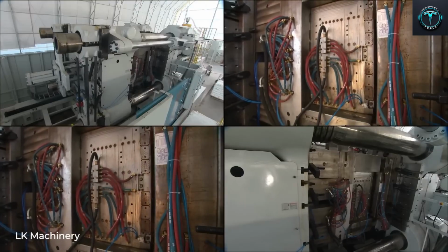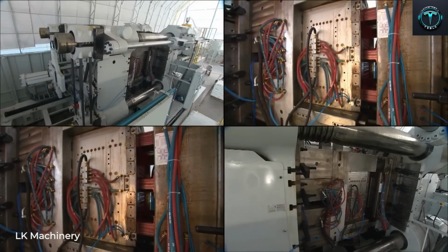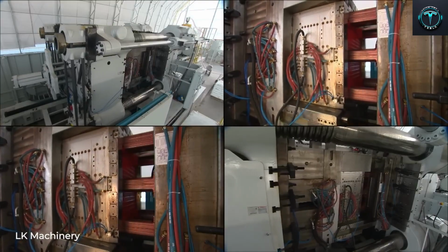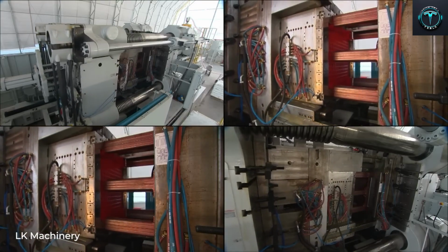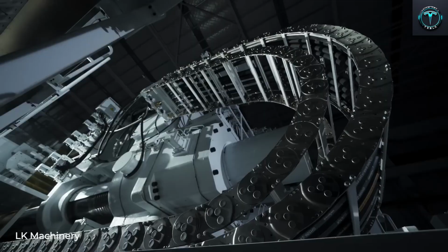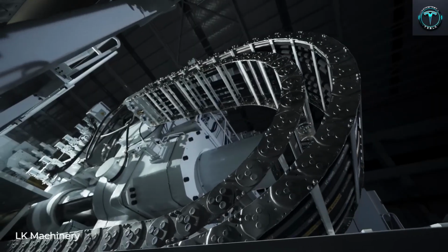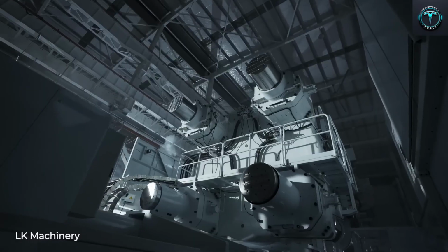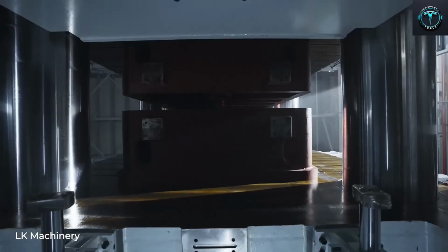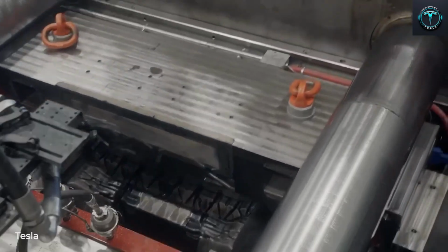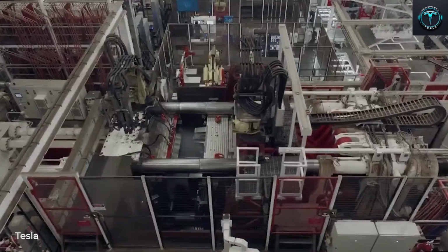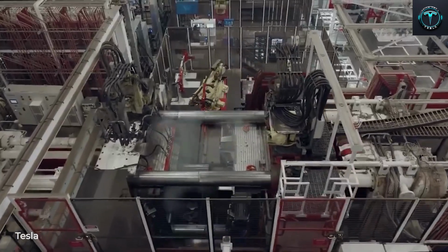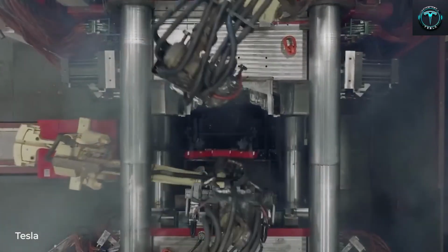The hardest part of all this is staying fast without losing precision. Inject the metal too quickly and you risk trapped air or flow defects weakening the internal structure. Inject it too slowly and the aluminum starts cooling before the mold is even fully filled. With a component this massive, one small section that doesn't fill properly can turn the entire part into scrap.